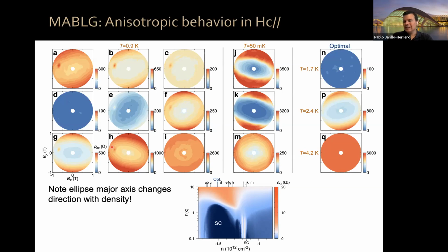Now, if it is changing with density, that means that it's highly unlikely that it will be just a result of pure strain, okay? Let's imagine that we have our magic angle graphene and we have stretched it very strongly in one direction. That would break the lattice rotational symmetry and just choose a direction, okay? But because we see that with charge density our nematic axis is varying, that means that it's not just a result of a very strong strain in the system, yeah? Now, let me leave it at that for the superconducting state. Let's look now at the normal state, and I'll come back to put everything together.